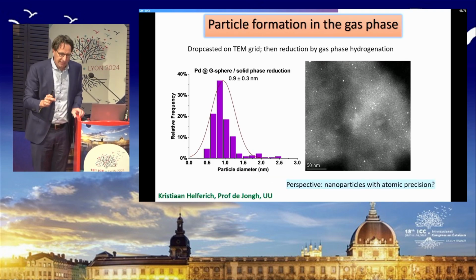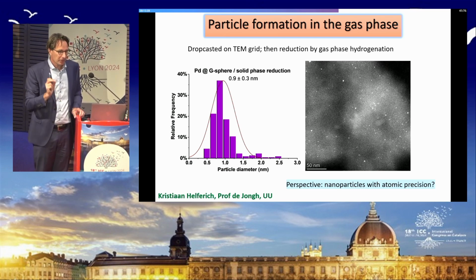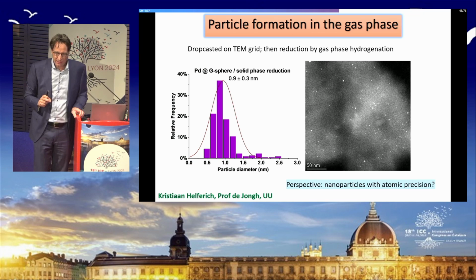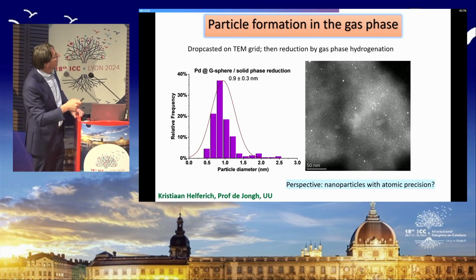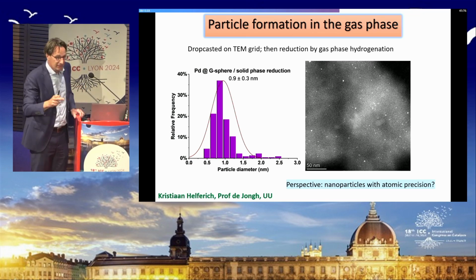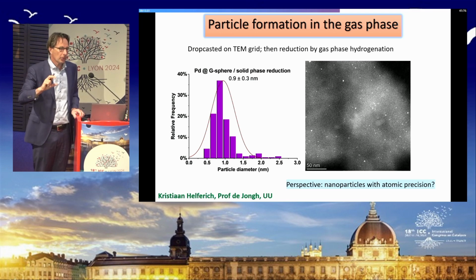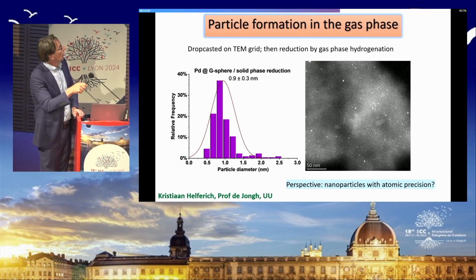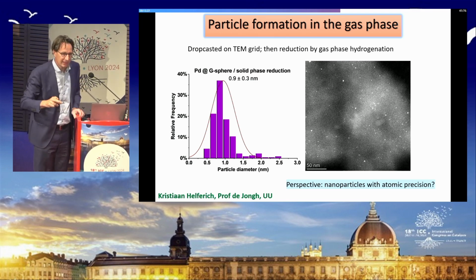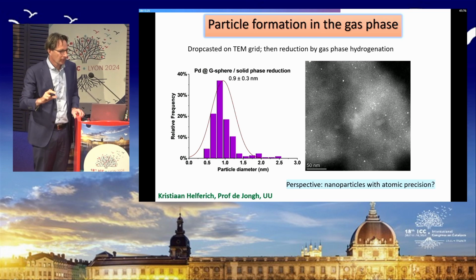Still triggered by the idea of forming nanoparticles with a precise number of atoms, we did the following experiment. So we drop casted these cages that were loaded with these metal complexes on TEM grids, and then we did a gas phase reduction. And because the gas phase